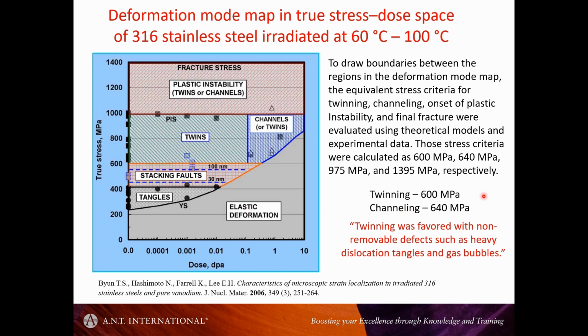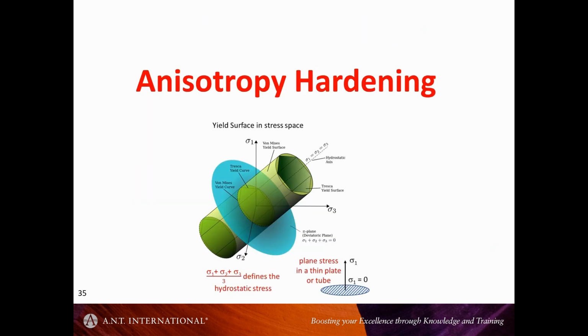What was interesting and worthwhile noting in Byun's work is that they found that in irradiated material, twinning occurs at a lower stress than channeling. And I haven't talked about channeling, but I will. That's going to be the main part of this talk, in fact. But just note that Byun's results showed that in irradiated 316 stainless steel, typically they would observe twinning at 600 MPa and channeling at 640 MPa if they were to demarcate the two, although by and large, they often got both mechanisms occurring. Okay, so I'm going to stop.